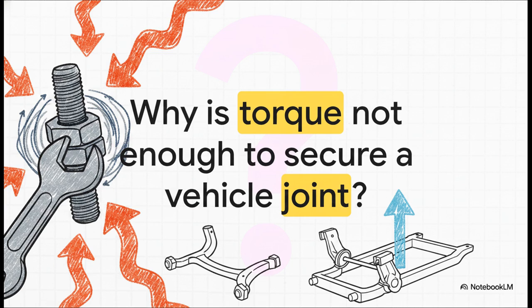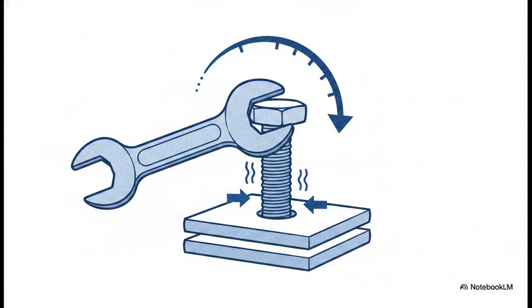Get ready for this. 85 to 90% of the rotational energy applied by the robot is completely wasted. Seriously. It just dissipates in overcoming the friction under the bolt head and inside the threads. Only about 10% actually goes into stretching the bolt to create clamping force. Because friction is so incredibly unpredictable, it can change from a speck of dust, a tiny drop of oil, or a shift in room temperature. Standard torque-controlled fastening can result in huge variations in how tightly the joint is held together. You definitely don't want that on your engine block.